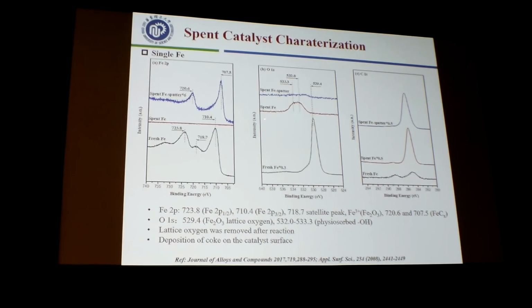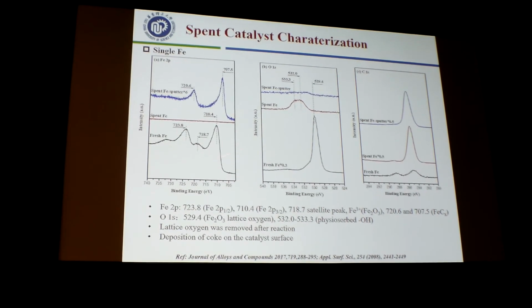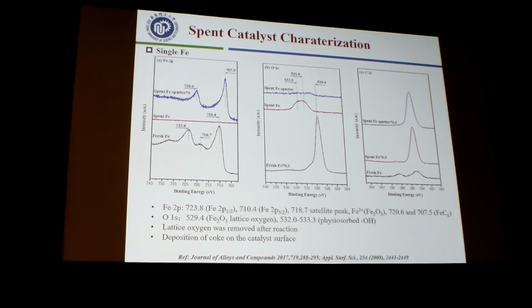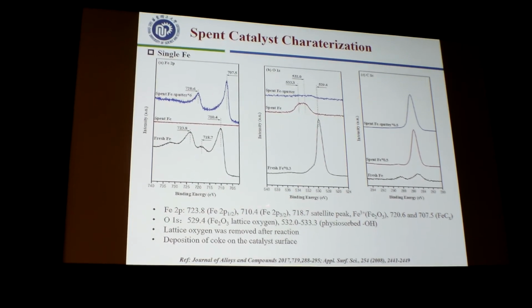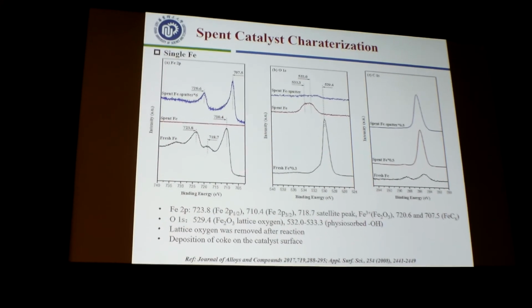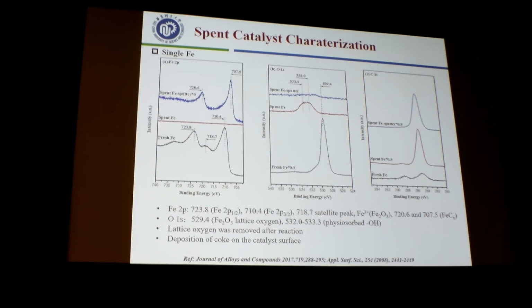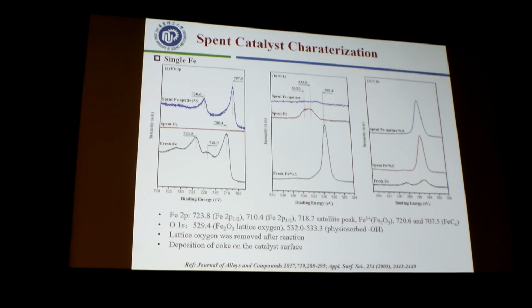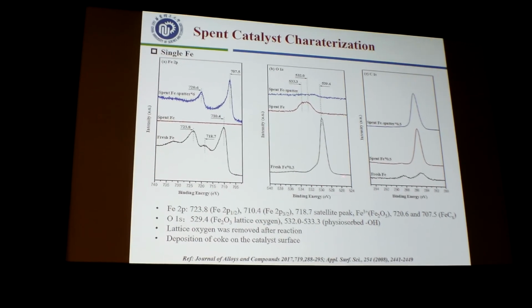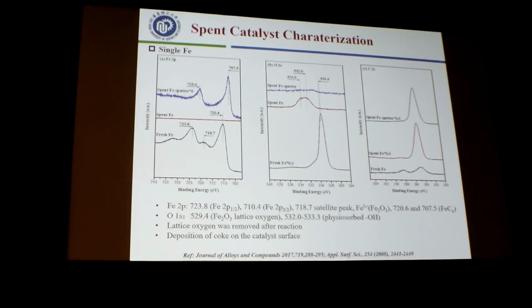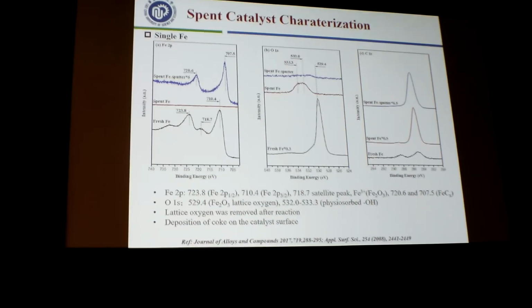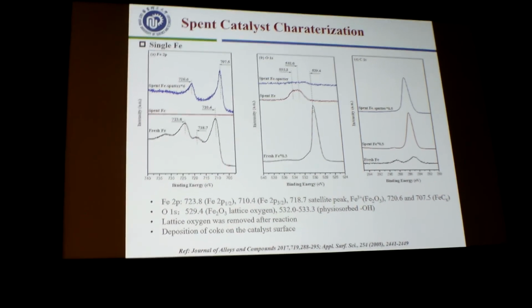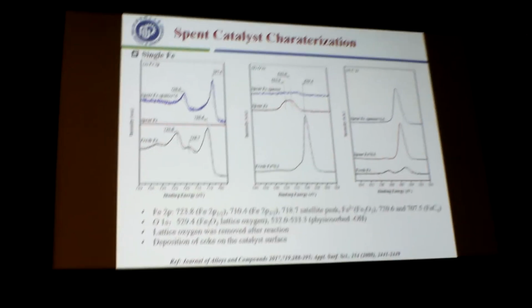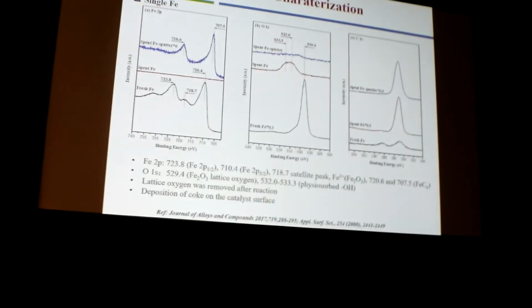So we also use the XPS to analyze the electronic properties of the catalyst, the spent catalyst, and the fresh catalyst. So from this result, we can see that lattice oxygen was removed after reaction here, and we can also show now the carbon XPS gives that the deposition was coke on the catalyst surface, but the coke deposition was suppressed after loading manganese.